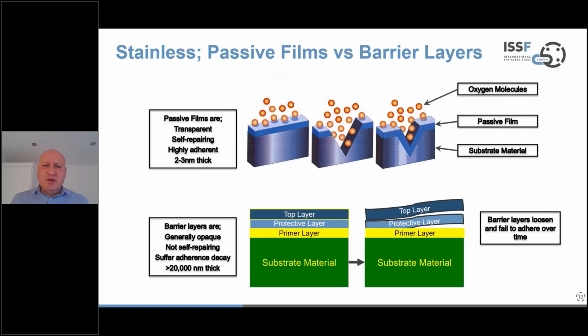So here's a quick overview of the passive film, and let's compare that with barrier layers. So in the top of this diagram, we have the notion symbolized of how the passive film works. So the spheres, the orangey colored spheres, are oxygen molecules. The blue section on the top is the passive film. Beneath that is the substrate, stainless steel. If you damage that passive film, the presence of oxygen immediately repairs the passive film. So the passive film is a fantastic feature of stainless steels, self-repairing, it's highly adherent, and it's very thin, 2 to 3 nanometers thick.